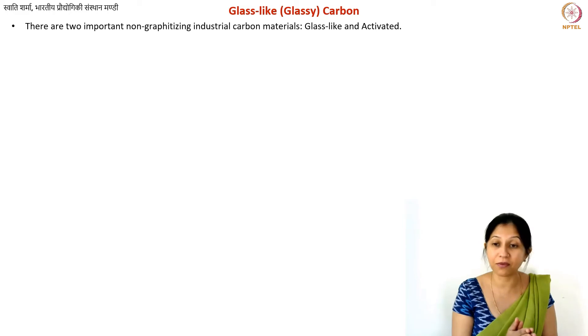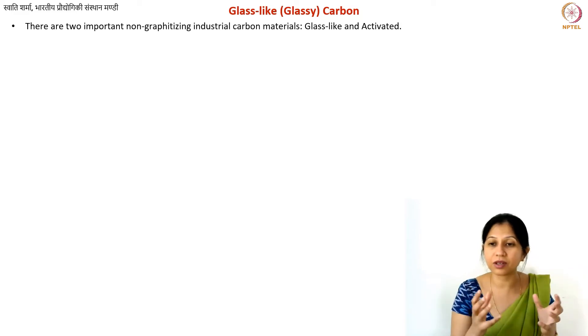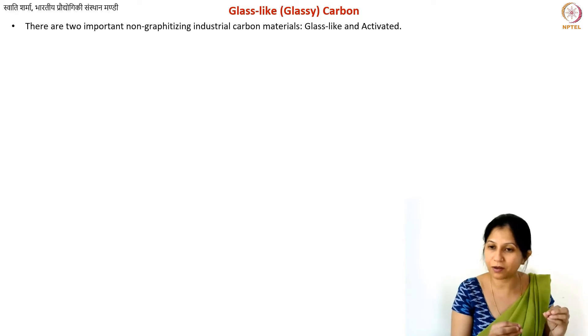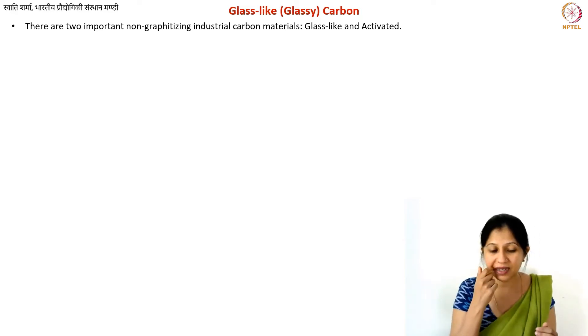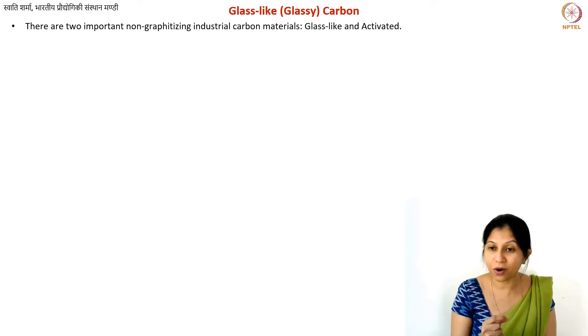They have fullerene-like structures, flakes which are curved, randomly distributed in all directions. If you find the average properties, you will find that in all directions they are pretty much the same. This is an important property which also makes them useful for certain applications where we do not want to use graphite — applications where you want properties that are the same in all directions. In that case, you can use non-graphitizing carbons.